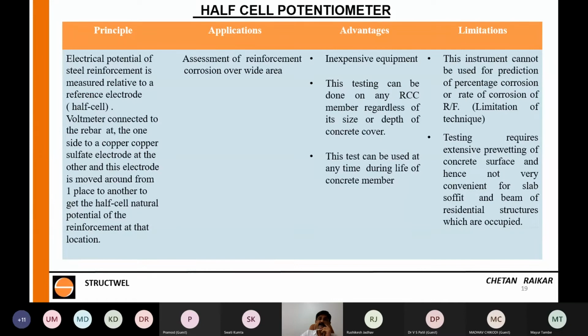Half cell potentiometer is not for prediction of percentage corrosion. See the limitations. I'm going a little fast because I'm sure I'll not be able to complete it within the time. Some unscrupulous laboratories tell you that we will give you percentage corrosion. There is a different instrument for percentage corrosion, not half cell potentiometer. And that instrument is not internationally used on construction sites, it is used in R&D works in the laboratory, but not yet used on the construction sites. It's not very popular because of the high level of inaccuracy that it still has.